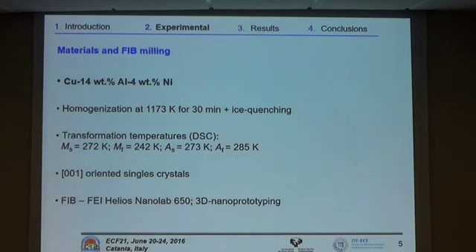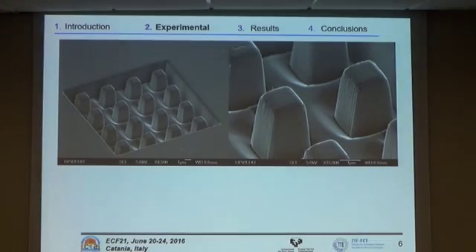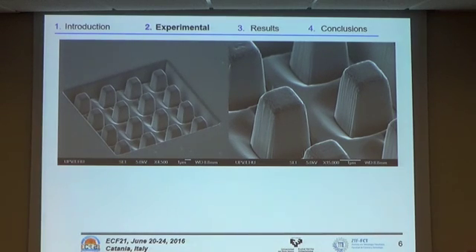And to mill the pillars, we have used an FEI Helios NanoLab with the 3D nano prototyping software to produce a range of pillars. We produced different arrays of pillars, and I will talk only about one array of pillars we have milled, which is shown in this image here. This is a magnification of part of this array, and as you can see, the section is square, but we also milled some pillars with a circular section, and although it is very tiny, there is a certain taper. That means that the faces of the pillar are not exactly perpendicular to the surface of the single crystal.